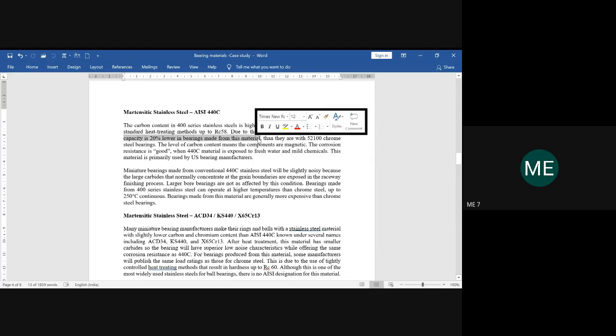If you are opting for chrome steel, you will be having still comparatively better load bearing capacity. But if you go for stainless steel in 400 series, it can achieve the hardness up to 58, not more than that. Due to this lower hardness, comparatively the load bearing capacity will be 20% below than that of the chrome steel what we discussed. So this is in comparison to 52100 chrome steel. So that I told you already.